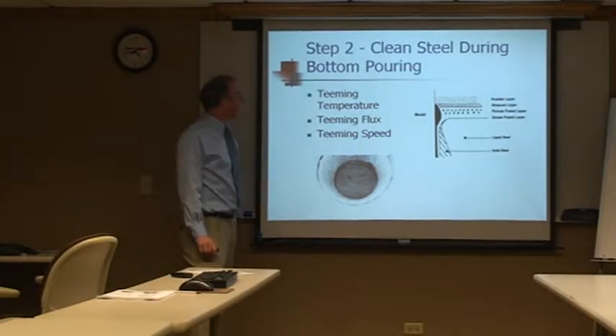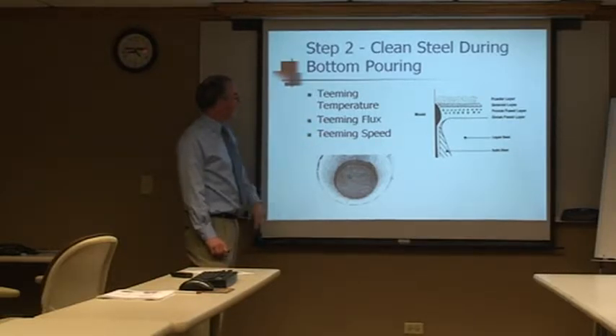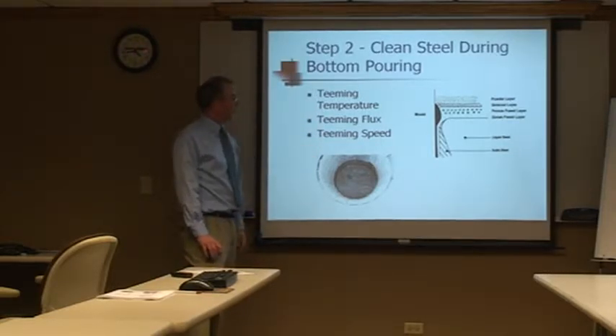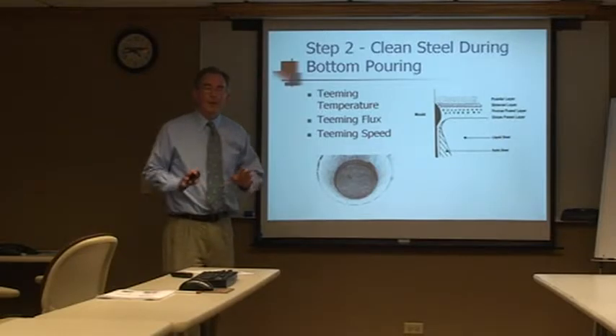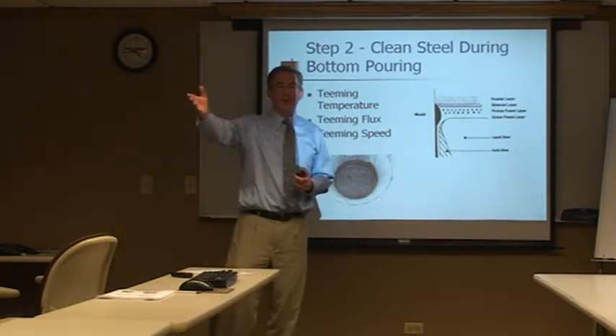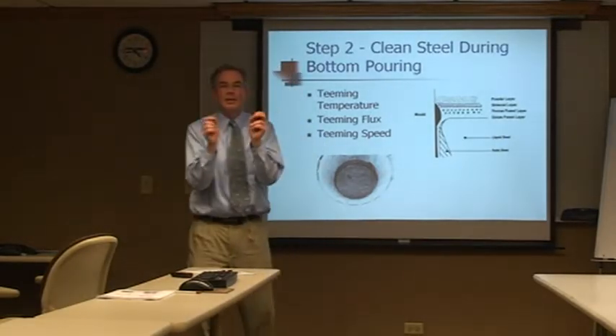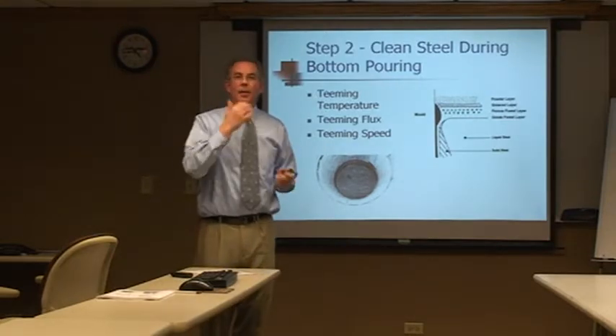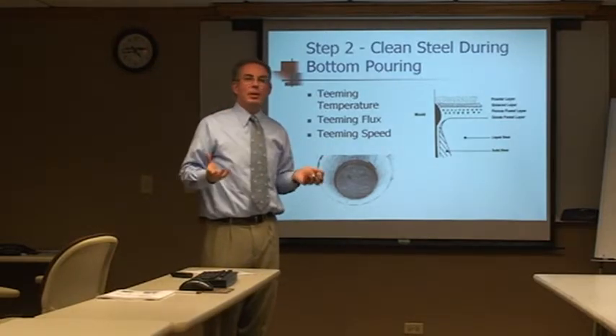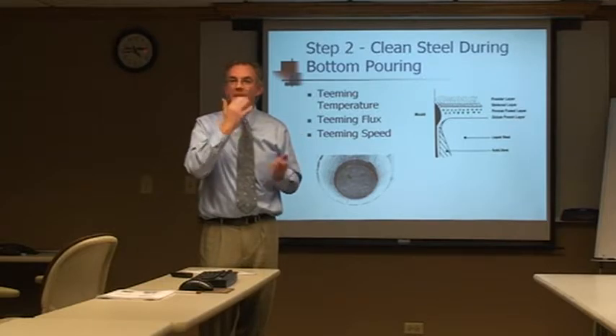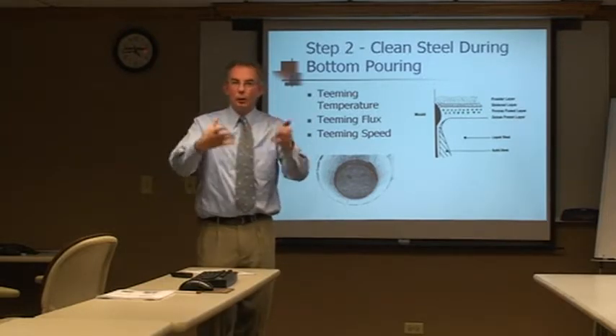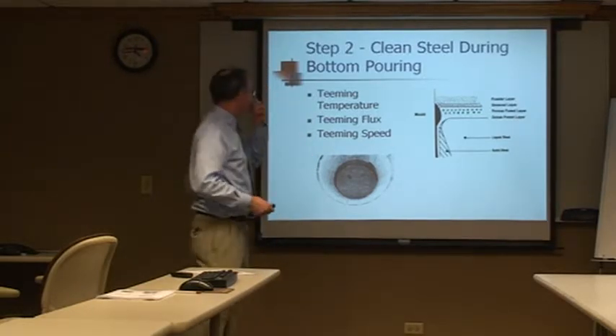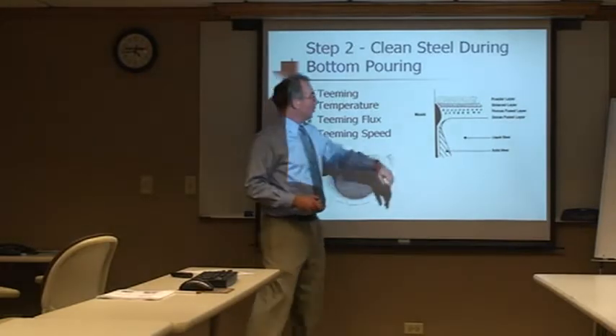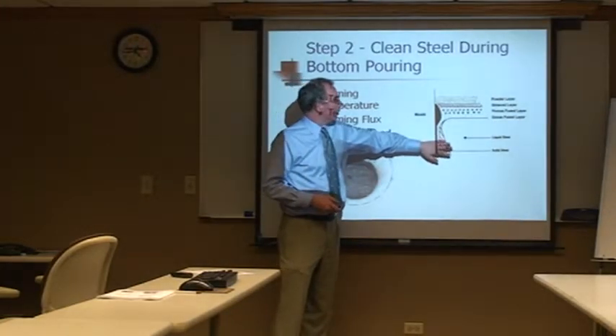So teeming temperature is critical. We'll talk a little bit about teeming flux and teeming speed. Now at this point, if there's going to be some residual alumina in there, that would be a small micro inclusion, an endogenous type inclusion, something that's coming from the actual liquid steel. What we want to avoid is creating any kind of exogenous inclusion.